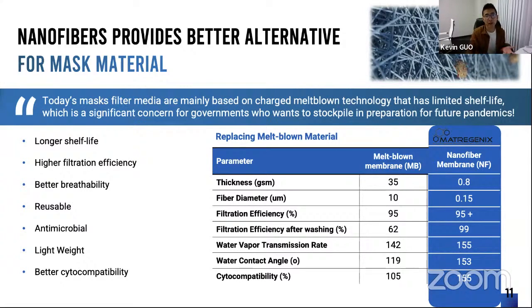It's become a significant concern for the government, who want to stockpile those masks for future pandemics. In this case, nanofiber provides a much better alternative due to its longer shelf life and the pure mechanical trapping system. At the same time, we also did a head-to-head comparison with the melt-blown filter media on different characteristics. From the data, we can say the nanofiber filter media has great advantages, including higher filtration efficiency, better reusability, lighter weight, and at the same time, better breathability.